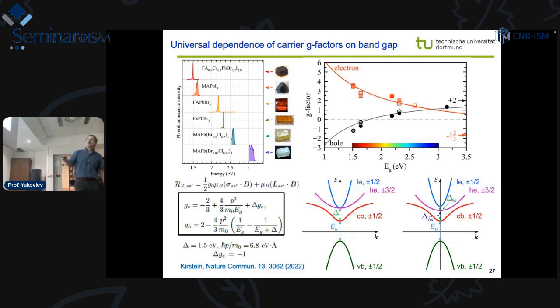And it was surprising for me, maybe for theorists also, that the very same set of parameters, like spin orbit 1.5 electron volt, matrix element 6.8, and this contribution of remote bands, allows us to describe the whole class of perovskite materials in the sense of the g-factors.